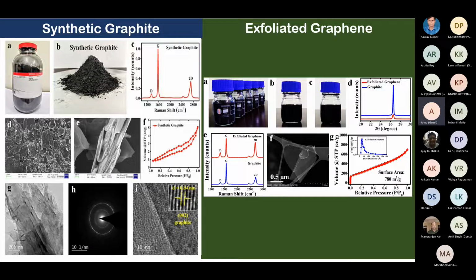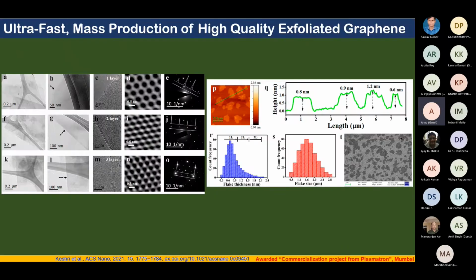When we measure the BET surface area, it shows 780 square meters per gram, and the initial surface area of the synthetic graphite was less than 1 square meter per gram. So this is definitely an indication that exfoliation must have taken place, right? This was our initial investigation of the powders we received after the exfoliation. After that, we started going much deeper inside this powder particle.